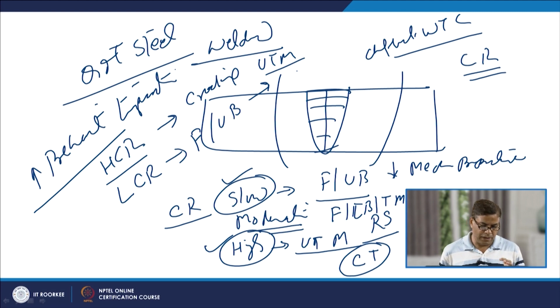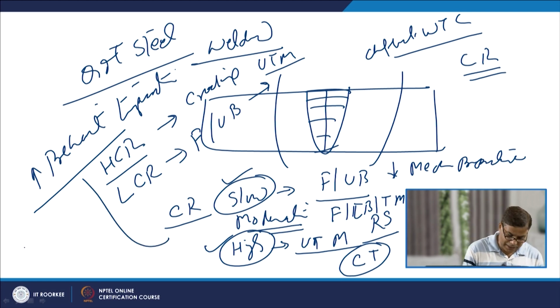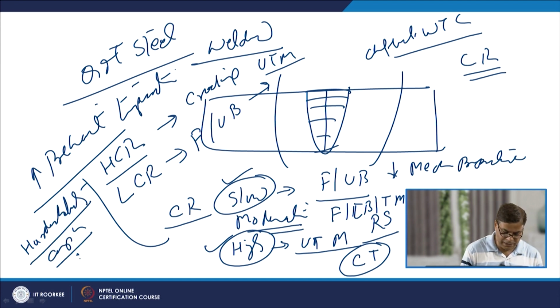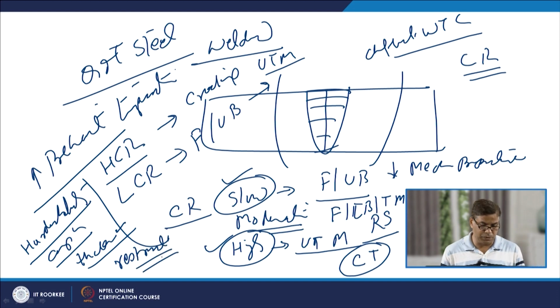So, an optimum preheat temperature is to be used, and it should be carefully controlled in light of the hardenability as dictated by the composition of the steel, the thickness of the plate being welded, and the kind of restraint conditions being used, so that unnecessary cracking tendency can be reduced and the required set of properties in the weld joint can be realized.